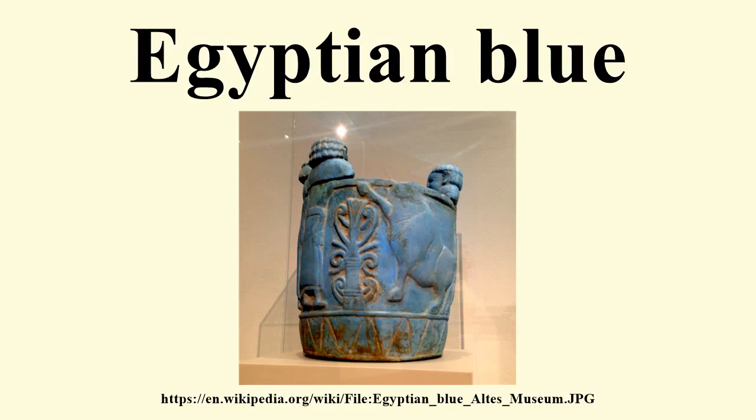It is also sometimes referred to in Egyptological literature as blue frit. Some have argued that this is an erroneous term that should be reserved for use to describe the initial phase of glass or glaze production, while others argue that Egyptian blue is a frit in both the fine and coarse form since it is a product of solid-state reaction. Its characteristic blue color, resulting from one of its main components, copper, ranges from a light to a dark hue, depending on differential processing and composition.